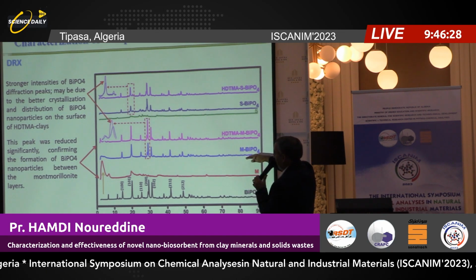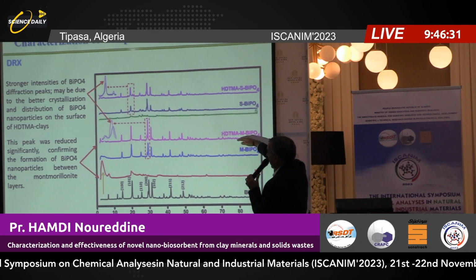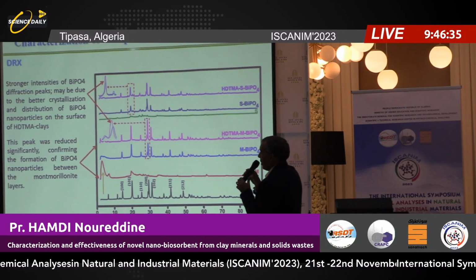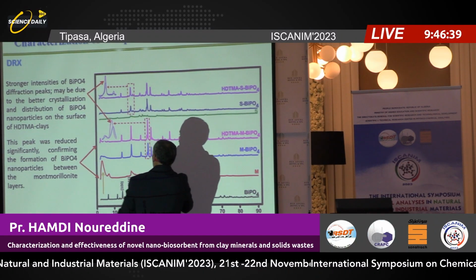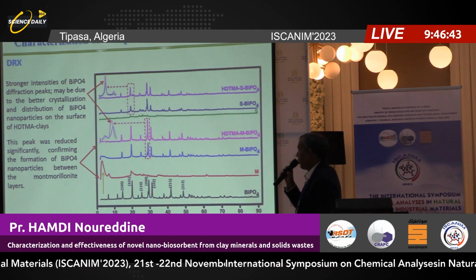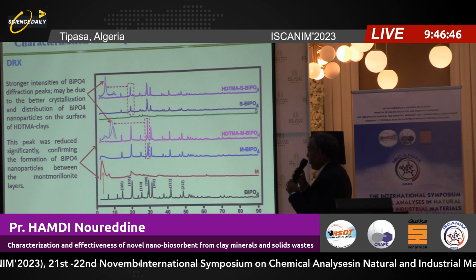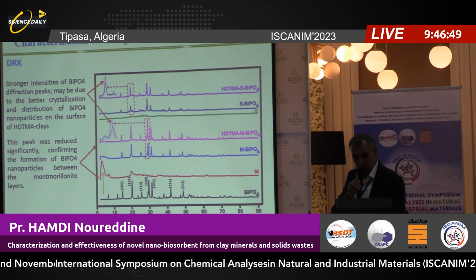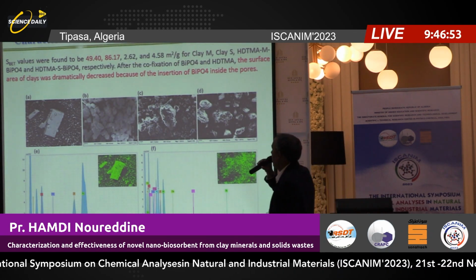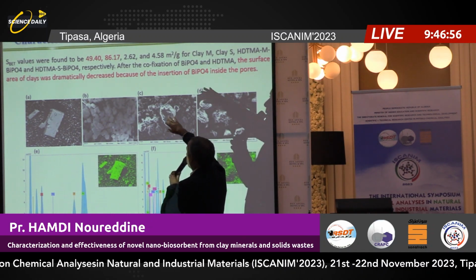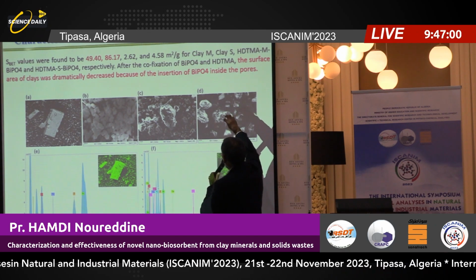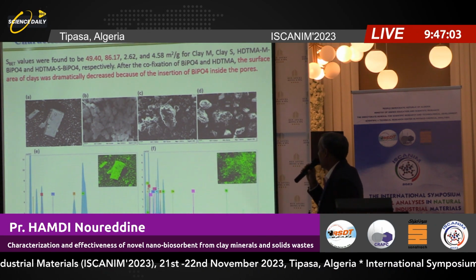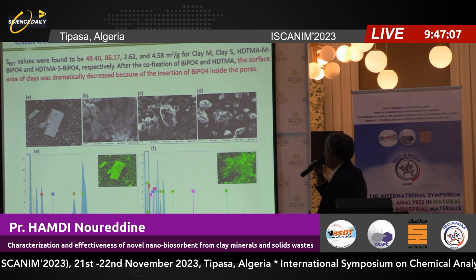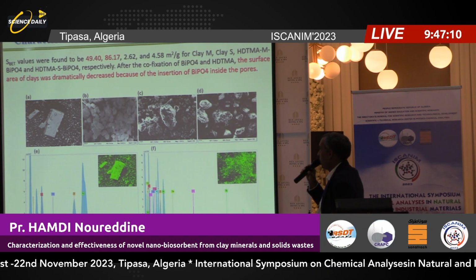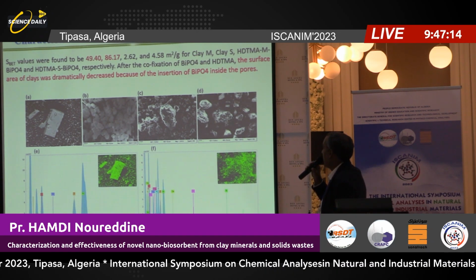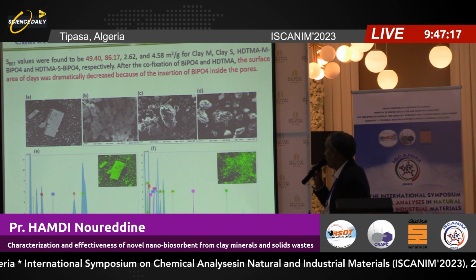When we have clay modified by the bismuth phosphate and by HDTMA bismuth phosphate, we find that this peak disappears. Why? Because the bismuth phosphate nanoparticle is in between the montmorillonite layers. The characterization by specific surface area gives an idea about the decrease of the surface area, because the nanoparticles are put in the porosity and block the nitrogen, entering the microporosity and nanoporosity. The surface area of the clay was dramatically decreased because of the insertion of the bismuth phosphate inside the pores.